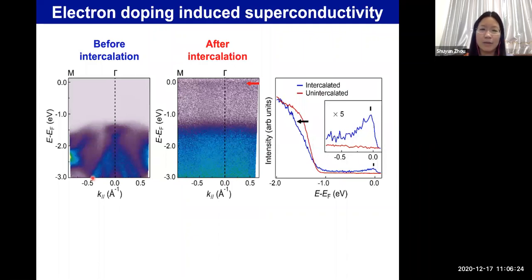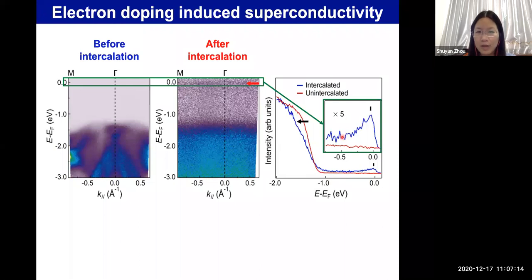Now, what happens? We perform ARPES measurements to look at the electronic structure before and after intercalation. Before intercalation, we see that within 1 eV below the Fermi energy, there are no bands. This is in agreement with the semiconducting property. Now, after intercalation, the ARPES data quality becomes somewhat worse because of some disorder introduced. However, here we can see that near the Fermi level, there's some intensity. And this intensity corresponds to this peak in the density of states near the Fermi level. So this tells us that this intercalation actually induces charges in the sample. And this electron doping is probably quite critical to the superconductivity here.